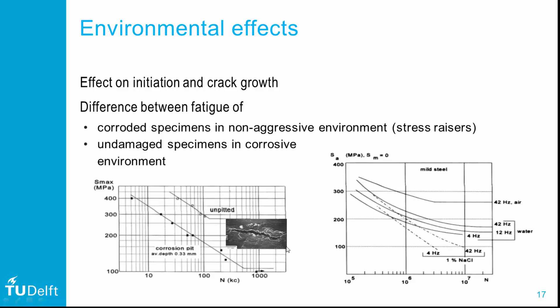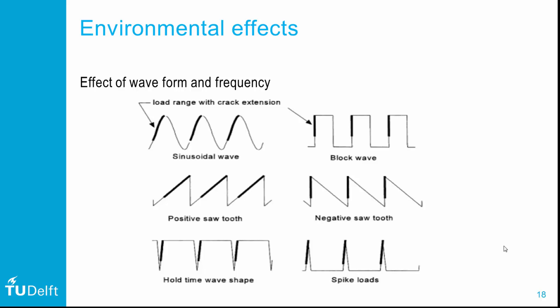The SN curves on the right illustrate the effect: water and salt water as environments reduce fatigue properties compared to air. Another aspect illustrated is the effect of frequency. If frequency decreases, fatigue properties reduce as well. At low frequencies the load cycle is slowly applied, giving the environment more time to access critical locations like the crack tip. Hence, one must consider the effect of load cycle wave shape and frequency — low frequency and slow ramp-up rates give more access to the environment, while short and steep ramp-up rates reduce the environmental effect.